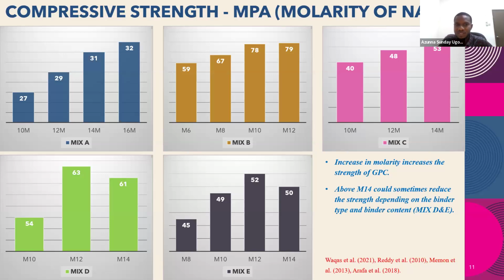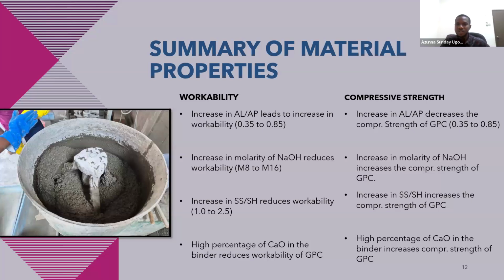So you're not advised to use a molarity that is too high. You're not advised to use a molarity that is too low. So that is why I said you can play the range of 8 mole and 14 mole, which is quite okay to give the desired strength. So now if you try to summarize the material properties of geopolymer concrete, it's as if workability and compressive strength are inversely proportional to each other. So for the first one, I said increase in alkaline liquids to alkaline precursor leads to increase in workability. If you increase the ratio, you have a higher workability. However, if you increase the ratio, you're going to have a lower compressive strength.